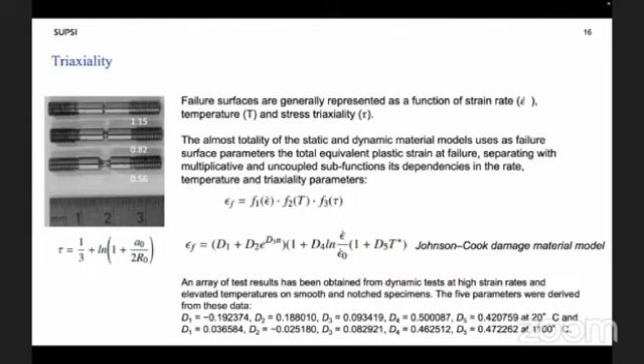As a conclusion, this preliminary investigation on the mechanical response of this commercial tungsten alloy was performed to analyze the effect of different temperatures, strain rate, and triaxiality. A methodology for testing materials at a high strain rate was presented. The methodology consists of performing dynamic tests in tension using the split Hopkinson tensile bar and heating the specimen using the induction coil system. The heating system is properly designed to concentrate the heat flux in the gauge length of the specimen.